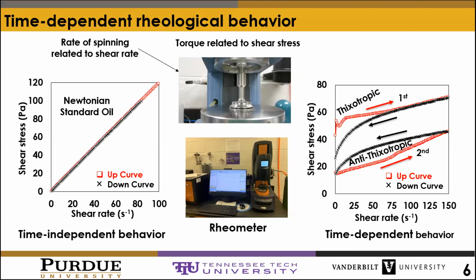But if the shear stress is a function of how long a fluid is sheared, then that fluid is said to have time-dependent behavior. The two forms of time-dependent flow behavior are thixotropy and anti-thixotropy, or negative thixotropy, or rheopectic fluid. So what is the quick difference between the two? The behavior is thixotropy when the down curve, during the decreasing spinning rate, the black curve, falls below the up curve, the red one, in a ramp up and ramp down loop experiment, as seen in the first loop on your right. The reverse is anti-thixotropy, which results when the down curve lies above the up curve, as seen in the second hysteresis loop.